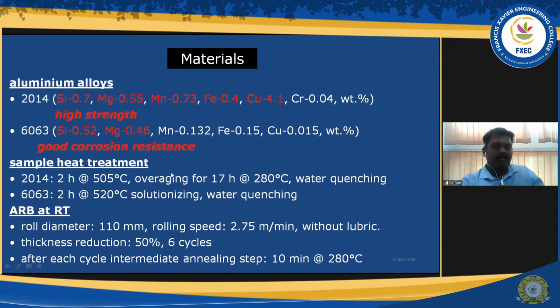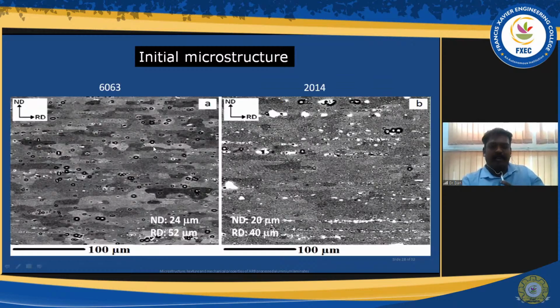Then they did some solution treatment before starting the experiment. Before starting the experiment, the microstructure looked like this. You can see the 6063 and 2014. They did three experiments. In the initial stage, they took the 6063 strips and stacked 6063 only. Then 2014 stacked with 2014 only. And in the third case, they stacked 6063 with 2014. They started with very coarse grain, like 52 micrometers in the rolling direction and 24 micrometers in the ND direction.